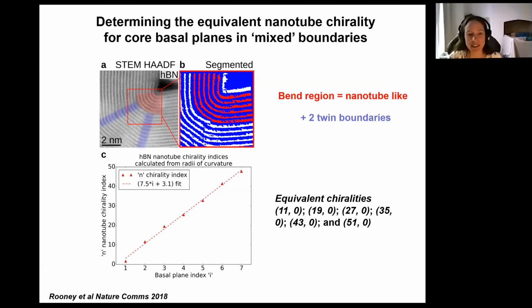And this again is what Aidan did. He had a look at the regions which you can see here, and we can actually look at these curved regions of graphite and look at the length of them, and we know the orientation because we're either looking along a zigzag direction or an armchair direction. And we can therefore consider these to be like carbon nanotubes or boron nitride nanotubes. So these nanotubes will therefore have a chirality, and we can assign the known chirality as a function of the distance from this inner core.